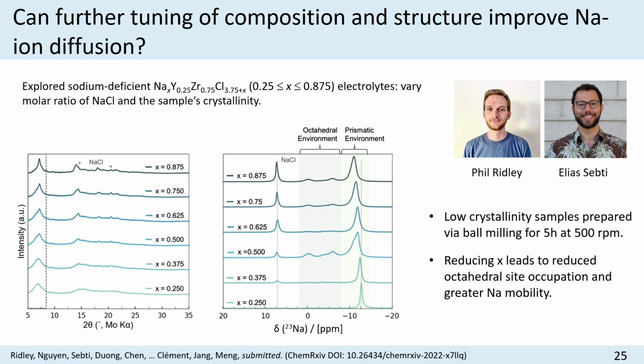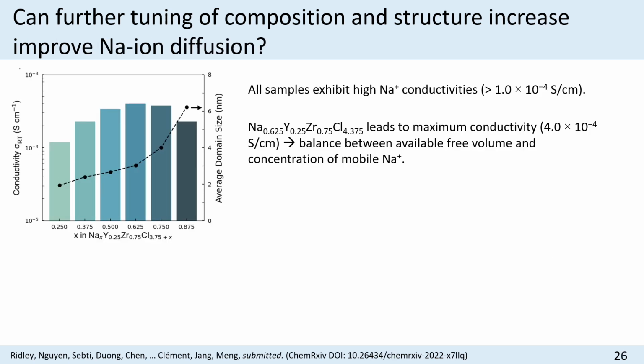And you can see that if you take an XRD pattern, these XRD patterns are very broad, suggesting that these materials are not very crystalline. You can also do some sodium NMR on these materials, and you find that you clearly have an evolution of the sodium environments in these materials. You're depopulating octahedral sites, which would have a shift in this region at very low sodium contents. What was interesting, though, is that the conductivity shoots up for these types of more amorphous sodium-deficient phases. And now you can reach conductivities almost millisiemens per centimeter.